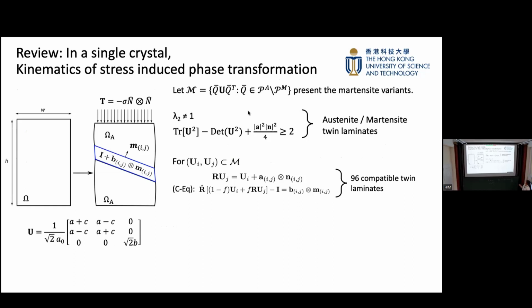And because lambda 2 is not equal to 1, the transformation stretch tensor still can make the twin laminate compatible with the austenite through some transition layer. We can calculate this crystallographic equation and get all the compatible twin laminates that can form in this pillar. In this specific case, we can get 96 compatible twin laminates.